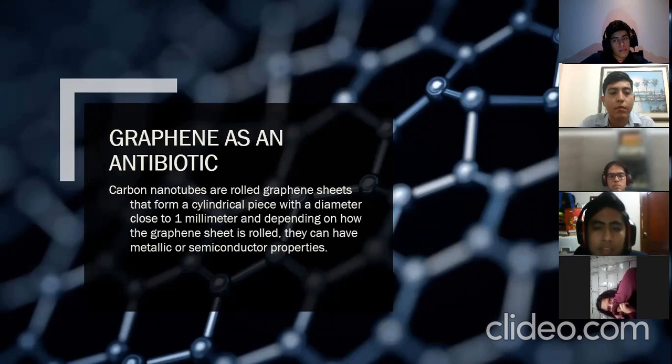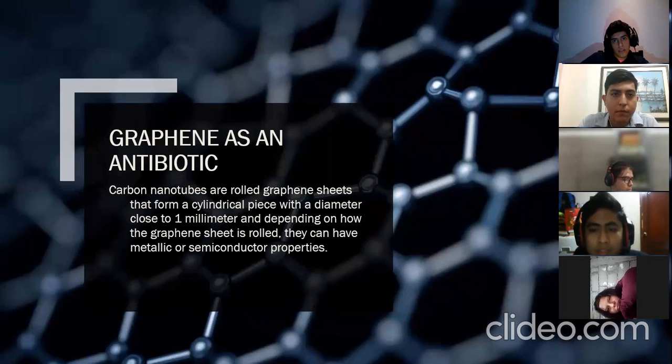However, in this study, it was possible to demonstrate the safety of the use of pegylated silver nanotubes, also making use of three cell lines: pulmonary, hepatocellular, and macrophage, and sufficient MIC values were obtained to cause bacterial death by damaging the membrane, creating reactive species, and eliminating cellular content without causing any damage to human cells.